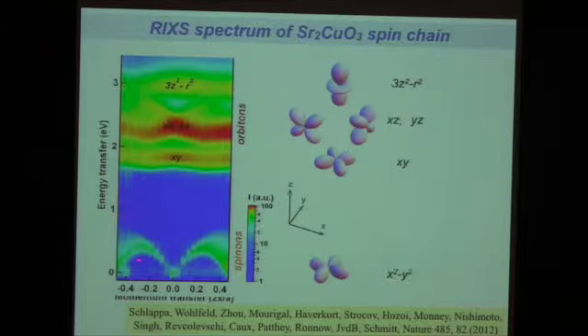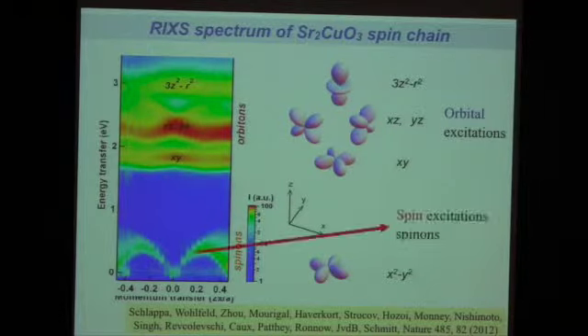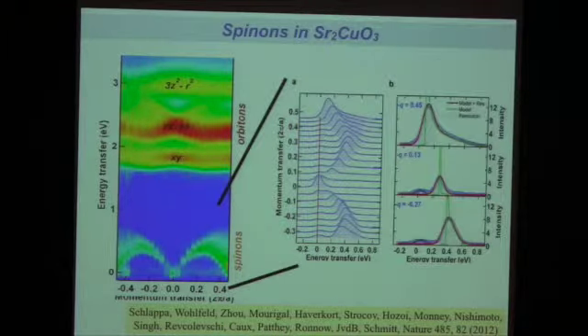So here is momentum transfer, this is energy transfer. You see at high energy transfer, there are the orbital excitations. These are my t2g orbitals, and again here my eg, so the 3z squared minus r squared. This we have seen before. Down here you see the spin excitations, they go up to half an eV or so. They are relatively high energy. So these are the spin excitations of the spin chain system. Now we know very well what those excitations are. They are spinons, and you can in principle calculate them from the Bethe ansatz solution of the 1D Heisenberg model. And this is what Jean-Sébastien Caux did.